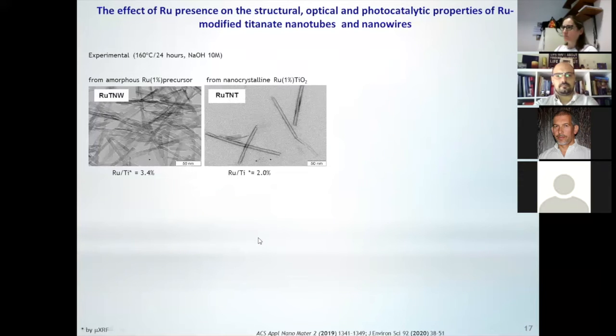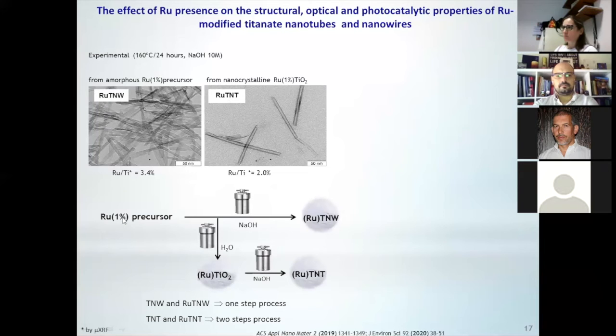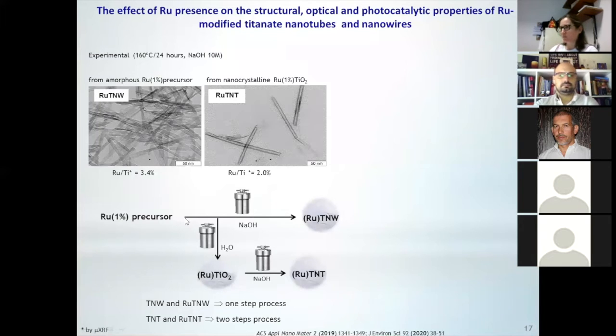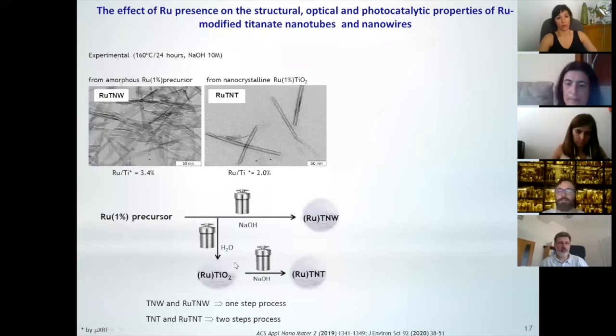Why? Well, remember, this sample is prepared directly, so we have only one chance to lose some of this ruthenium during the process. In this case, we can lose some ruthenium here or during this process. So the fact that we have a lower amount in the titanate is okay and is in agreement with the experimental part of the work.